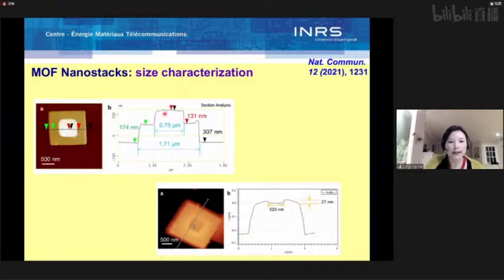About the sizes, we used AFM to characterize, and here it shows a typical MOF nanostack structure. The top nanoplate has a lateral size of about 0.75 micrometer and a thickness of around 130 nanometers. For the bottom nanoplate, the lateral size is about 1.7 micrometers, and the thickness is about 174 nanometers. Interestingly, we also observed some nanoplates where the top plate is missing, and here we can see a little dent of about 27 nanometers. We think this was caused by the missing of the top plate for whatever reasons. It looks like the top nanoplate is partially embedded into the bottom large plate, so the interface bonding can be quite strong.